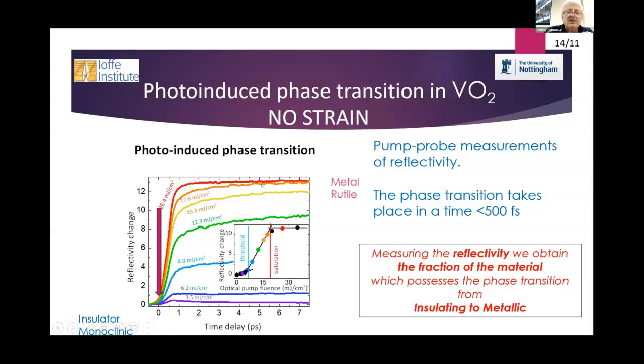Such experiments have been done in many works, and for us, this is just characterizing the material. We see that above some threshold, the phase transition starts. The amount of material which undergoes phase transition goes up, and then at some point there is saturation, which means all material is transformed to another phase, the rutile metallic phase in vanadium dioxide.